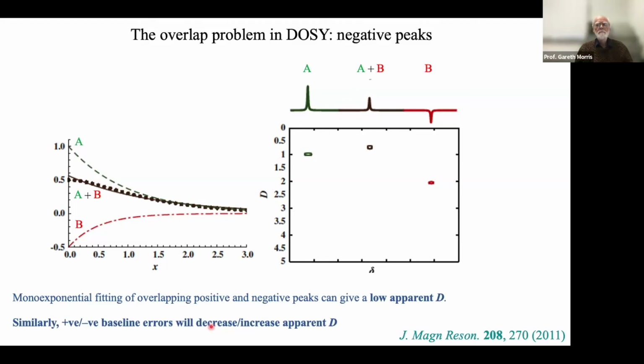Early on, I mentioned that our, quote, typical, i.e. best ever, DOSY spectrum had the C13 satellites lining up with the methyl signal. That only happens if you've got a really good flat baseline, because even a small baseline error will result in C13 satellites appearing to diffuse more rapidly or less rapidly than their parent signal.